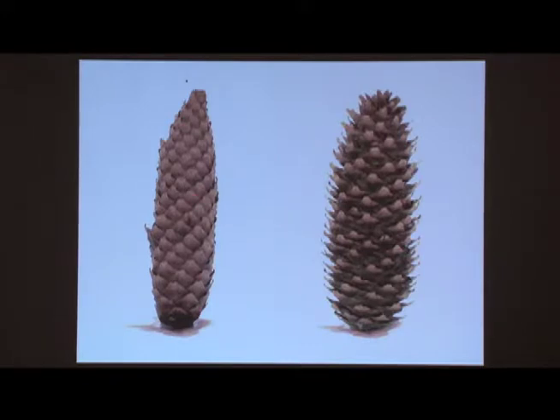The spruce cone grows in a wet, moist state, with a high moisture content within the fibers, at fiber saturation point, and then it dries, and once the environment has reached suitably dry conditions, it opens, seeds are released, and that's all embedded as a material behavior within the fiber structure. Funny thing is that obviously the spruce cone just needs to do this once, but it works perfectly over 500 cycles. Tested that a lot. So here you can see again, moisture content decreases, and by that the scales open.